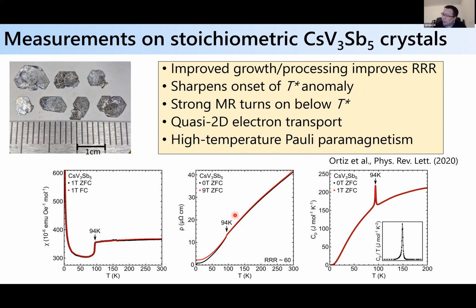If you do longitudinal magnetoresistance and apply a 9 Tesla field, I don't have it plotted in terms of percentage, but it's a several 100% MR effect that occurs at low temperature. You can see the divergence starts turning on more or less below this 94 Kelvin transition. And you also see the anomaly in heat capacity. It's a very sharp peak, very suggestive of a first order phase transition, although we don't see any real hysteresis. But we haven't looked at the sub half Kelvin regime, so we haven't looked with very high temperature resolution for the hysteresis.